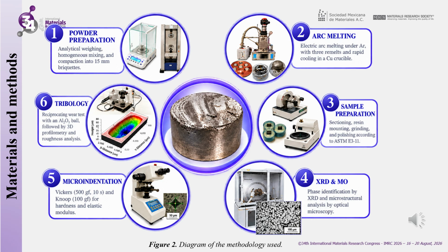The briquettes were melted using an electric arc melting process in an inert argon atmosphere, with 3 remelting cycles carried out to ensure homogeneous composition and reduce segregation at 3000 degrees Celsius. This process yielded ingots of high purity and homogeneity. Following the acquisition of the ingots, they were subjected to a process of precise cutting utilizing a precision cutter and subsequently mounted in polymer resin. This procedure was undertaken in strict accordance with the guidelines stipulated within the standard ASTM E3, with the objective of ensuring optimal sample preparation. The mounted specimens were subjected to a sequential process of roughing and polishing.